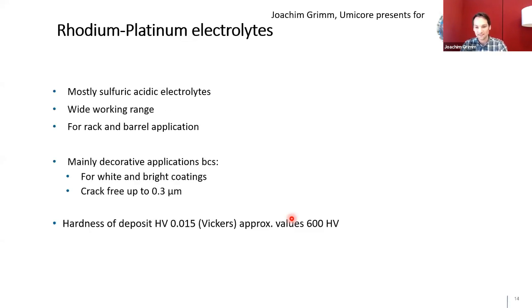The Rhodium-Platinum electrolytes are the same, sulfuric acid based. They have as well a wide working range. You can use them for rack and barrel applications, and mainly for decorative applications, possible white and bright, up to 0.3 microns, as the platinum is a bit more, I would say, brittle compared to the mixtures of rhodium-ruthenium. So the reachable final layer thickness is not so high. But 0.3 micron is already totally enough for jewelry applications. So next slide I want to go.